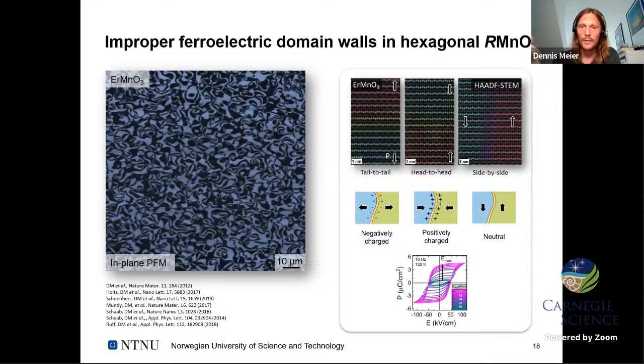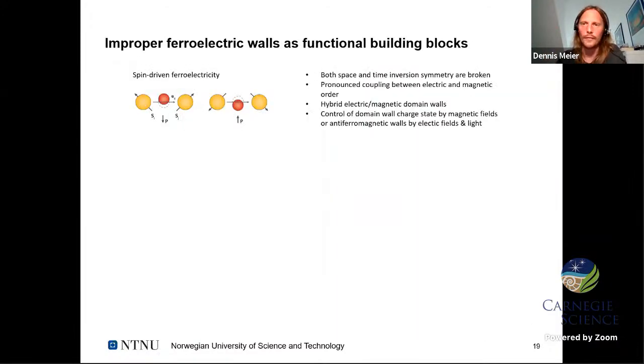Before, it was a spin system generating very unusual domain walls. Here, it's a structural order parameter, which gives us, in one and the same system, tail-to-tail domain walls, which are negatively charged, head-to-head domain walls, which are positively charged, or also neutral domain walls here, where we have a side-by-side configuration. So all different flavors, fundamental types of 180-degree domain walls are around, and we can still switch them when we play it right by application of an electric field. So we are also not missing the advantages of normal ferroelectrics, that we can move this around and play with the domain walls and the ferroelectric domains.